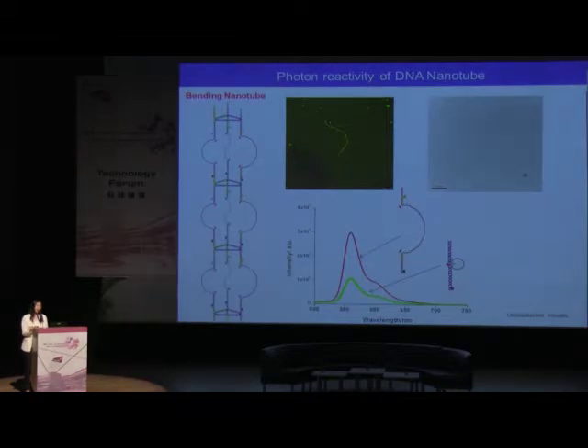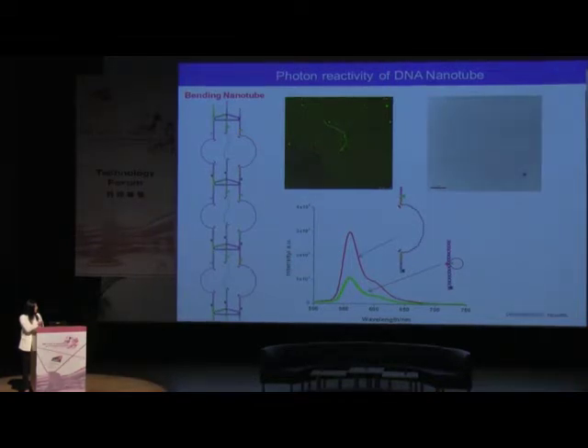And the opening or expanding of the cavity is also confirmed by the fluorescence measurement, because here we have designed the strand with the dye and the quencher. Before excitation, they are close to each other, so that's why the fluorescence is decreased. But after expanding the nanotube, the distance between the dye and the quencher is far, so the fluorescence from the dye will be increased dramatically.